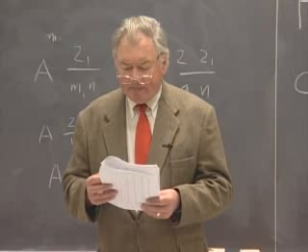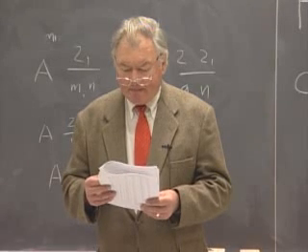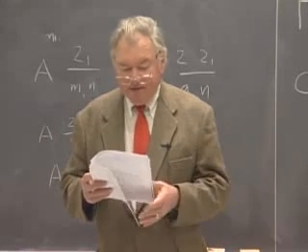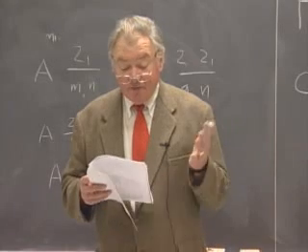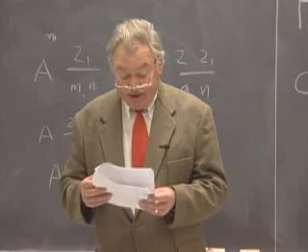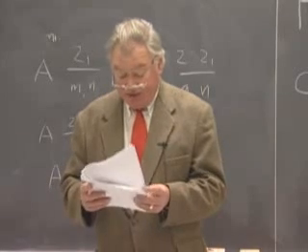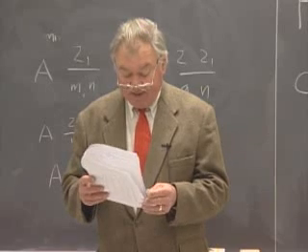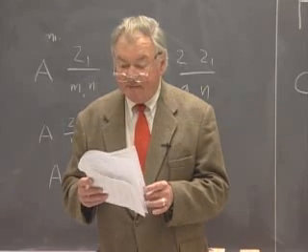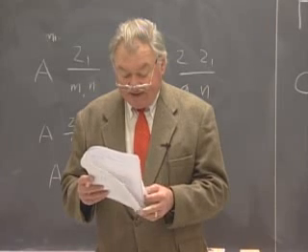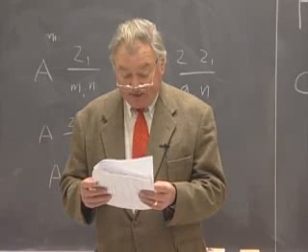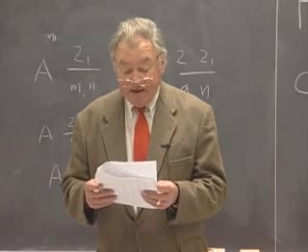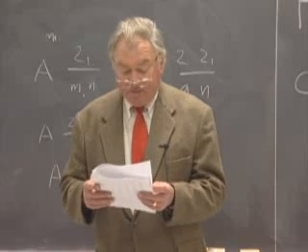alternative. Something like P4, 4 is in the direction of the C-axis. There are twofold axes parallel to that, but the symbol that is used for the symmetry part of the space group symbol looks very, very much like the symbol for the point group. So these are pretty much self-explanatory. Notice that there are 2 kinds of lattices for tetragonal crystals, either primitive or body-centered. So you see families with P for primitive or I for body-centered.